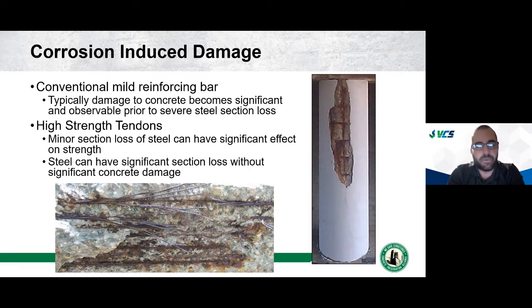So the takeaway here is, if we're assessing structures and we know that they're pre-stressed elements or post-tension elements, we need to take more consideration of their condition, because if we're using the same visual cues like cracking, delamination, and spall to indicate, hey, we need to start doing something, we may have much more significant damage in those elements than we would with conventional reinforcing steel, which we historically have based those assumptions on. So you may want to do more advanced investigative techniques to understand those conditions before they become a structural issue.